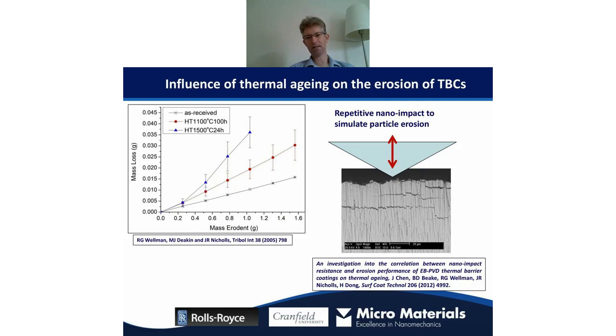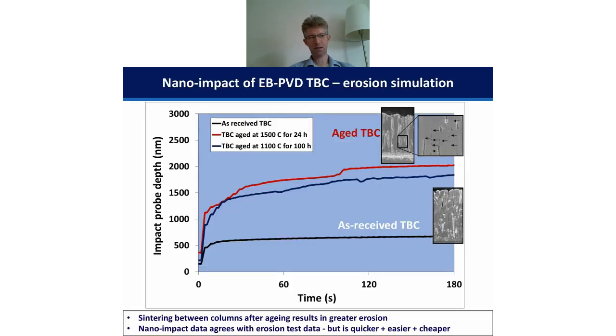So we can simulate this erosion test really quite simply by using the repetitive nano impact test. So we typically hit at the same position on the surface. We can cause the cracks, and we can follow that deformation behavior. So here is an example of how it's working. So here we have 3 different impact test results. You can see the tests are really quick. They're only a matter of, in this case, 3 minutes. And we get exactly the same ranking of wear rate that we do in the much longer erosion tests.